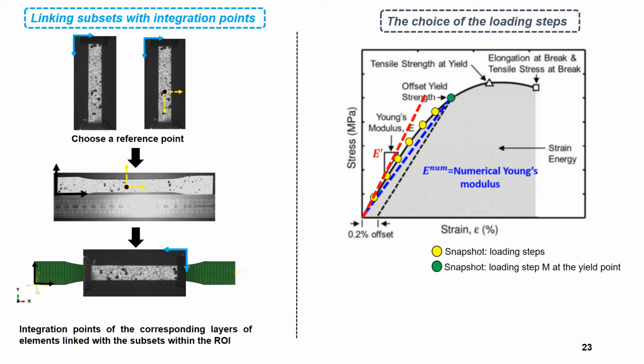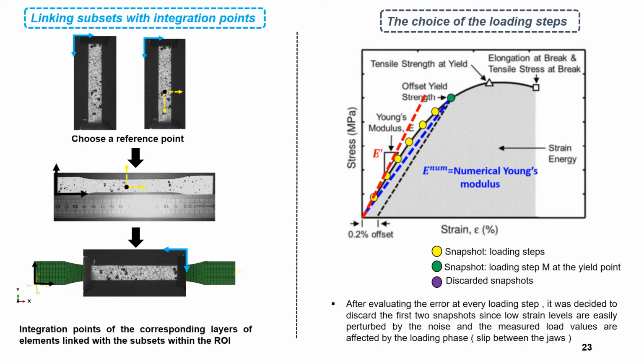Also, 7 loading steps were chosen from the start of the test to the yielding point, but later we discarded the first two, because low strain values are easily perturbed by the noise of the DIC measurements, and the measured load values are affected by the loading phase slip, or the slip between the jaws, observed in the beginning of the test.